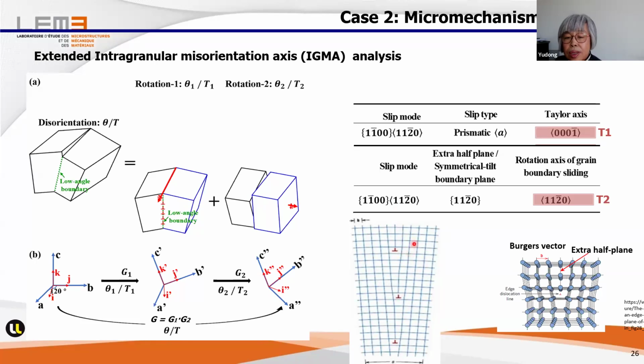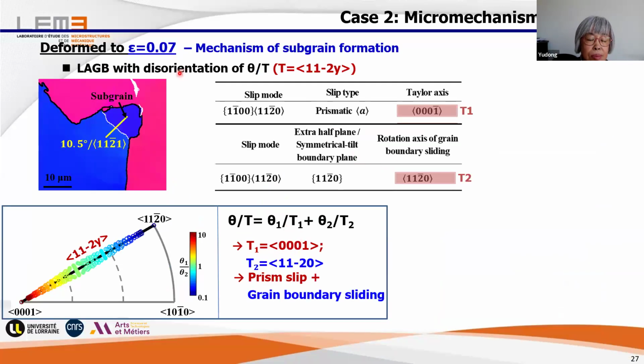Is it possible that this part of the crystal related to this part of the crystal can be rotated with an axis perpendicular to this extra half plane normal? And then for prismatic slip, the direction perpendicular to this extra half plane is this axis. And then she made a combination of these two, and then she made a simulation.